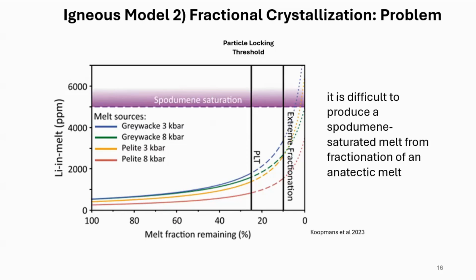We said, well, even if it's extreme fractionation, and we're at 10%, because the models are rough guesses, still by taking these values here, where those stars in the previous diagram are, up to 200 to 400 ppm, when we fractionally crystallize it, by the time we get up to 90% fractional crystallization, we're still only at 3 to 4,000 ppm lithium. So fractional crystallization doesn't seem to work.